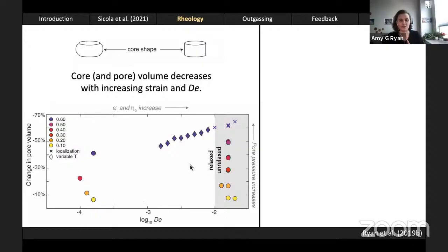So the materials that have experienced the greatest reduction in pore volume are those deformed at high Deborah number conditions and to high strain. And this is significant because what the change in pore volume is really telling us is a change in pore pressure. I'll remind you that CO2 has a very low solubility. The CO2 is not being forced back into the melt in these systems. And for the most part, as you'll see, the cores themselves remained impermeable. So this relationship between volume and pressure holds pretty well. And we know that these highly deformed samples and those deformed at high Deborah number conditions contain pores that are the most pressurized.